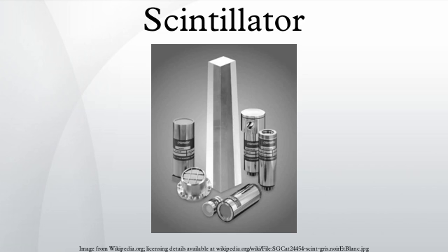Organic scintillators can be dissolved in an organic solvent to form either a liquid or plastic scintillator. The scintillation process is the same as described for organic crystals. What differs is the mechanism of energy absorption. Energy is first absorbed by the solvent, then passed on to the scintillation solute. In inorganic materials, the scintillation process is due to the electronic band structure found in crystals and